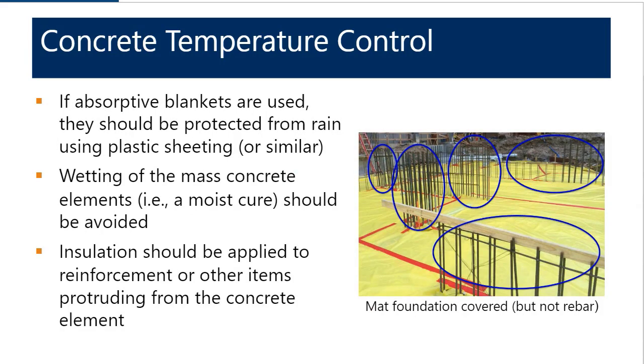So if you are using absorptive blankets, something that's going to absorb moisture or water if it rains, for example, you'd want to put down some plastic sheeting. And so you can see in the right-hand side of the slide that plastic sheeting was installed because an absorptive blanket was used. And so the idea here is that the water will have a cooling effect and can cause your temperature differentials to increase. And so that's why we recommend that wetting of that mass element should be avoided. So many specifications often require that a wet cure be applied to concrete elements. It's our position that wetting of the mass concrete element has a cooling effect and increases the likelihood of larger temperature differentials, and can therefore increase the likelihood of thermal cracks.